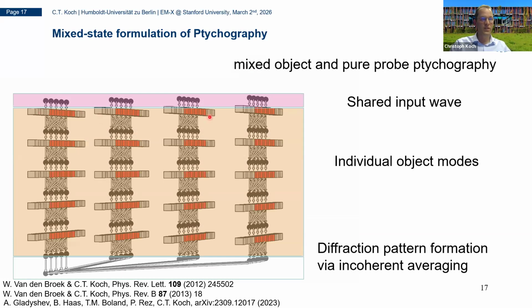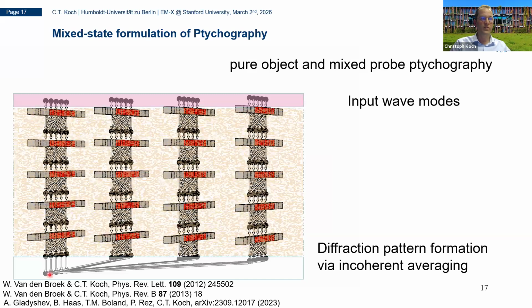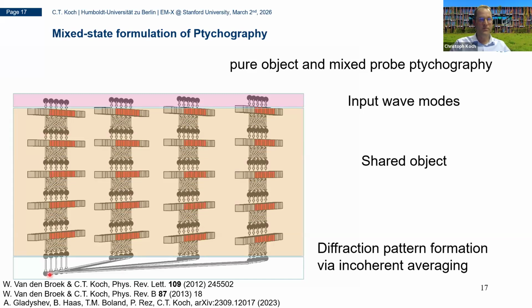And so they might either have a shared input wave, and then you have different objects, and you then basically put the same wave into each of these objects and then have different configurations of potential in here and sum them all up. Or you can also have, of course, a pure object, but different probe modes. This would not simulate the thermal diffuse scattering, but would actually account for the partial spatial coherence, which has been developed in the group in Sheffield on this.